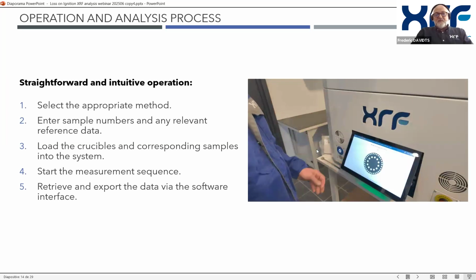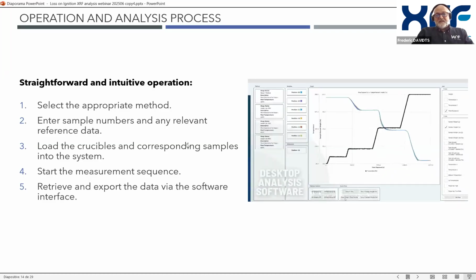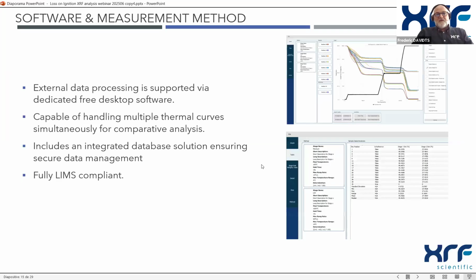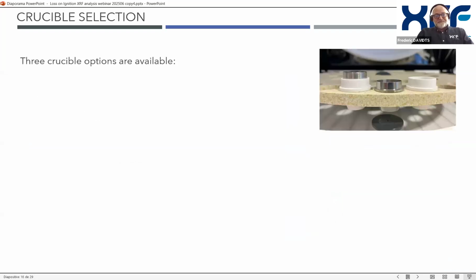At the end of the cycle, we will retrieve the results, which can also be transferred elsewhere. And of course, we have a program to deal with all the results. The main important result in most cases for XRF is the loss in percentage, the loss at the final temperature. But in some cases, it's interesting to check the curves and see where we have a loss, for more qualitative analysis. And really important, it's LIMS compliant, meaning that the data can be transferred directly to a dedicated location. And of course, no need to be at the machine to work with the data.